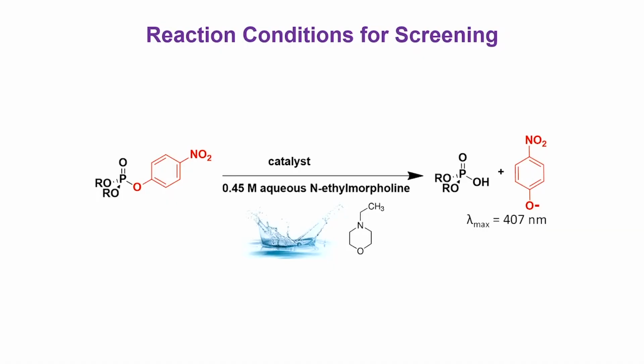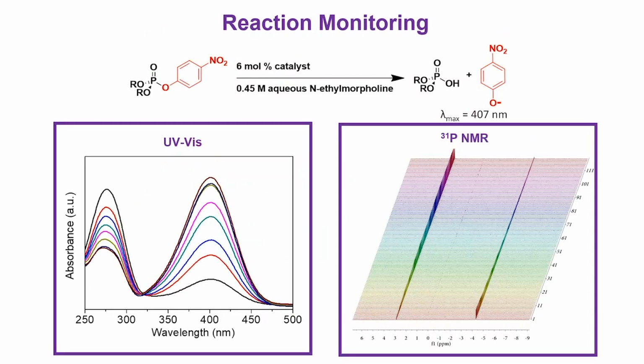The reactivity, how we test this reaction: if you take the surrogate, this is our surrogate, and you do the catalyst with some base, and here we use ethylmorpholine, and a beaker of water, just for the ease. Now, we could monitor this reaction because the product is yellow. However, the actual agent has no product that is yellow, so we need to use a different way of testing that, and we use in situ phosphorus NMR. Regardless if you have the in situ NMR or the UV-Vis, you'll end up getting the same results.